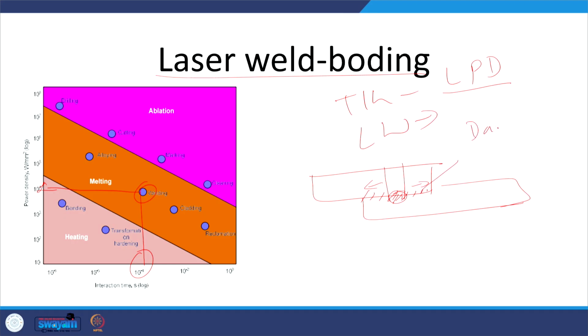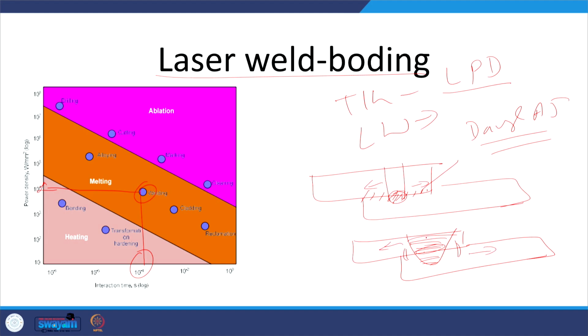Therefore, the damage to the adhesive joint is minimized when laser welding is used as compared to TIG welding. In TIG welding, we supply a lot of heat. So, a large area of the top sheet melts a little bit, the bottom sheet will melt, and the metallurgical bond will certainly be created, but this will cause thermal damage to the adhesive joint to a greater extent, because a significant amount of heat is supplied for developing the TIG spot as compared to laser welding. So, laser welding offers much better joint strength and performance as compared to the TIG adhesive joint hybridization.